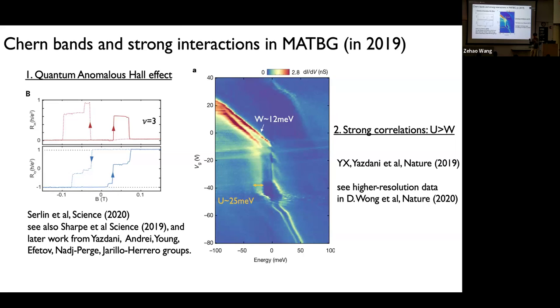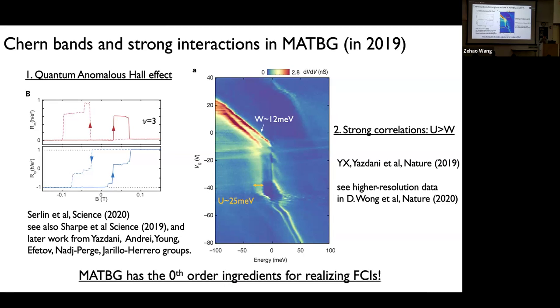Like, at zeroth order, for example, what the Hubbard U or the Coulomb interaction is. And then you can also compare with the bandwidth, characterized by the width of the tunneling density of states. And you see that, and you heard, I think, from Ming, if you want strong correlation, then you want U larger or much larger than W, and it looks like we are in good shape here. So at that time, I think MATBG was probably the most promising candidate if one wants to look for FCI, because it has a Chern band, and it has strong electron-electron correlation. And at that time, I was about to finish my PhD, and I was thinking, what should I do? I've been following FCI for quite a while, and it sounds like this is a very exciting place to jump in.